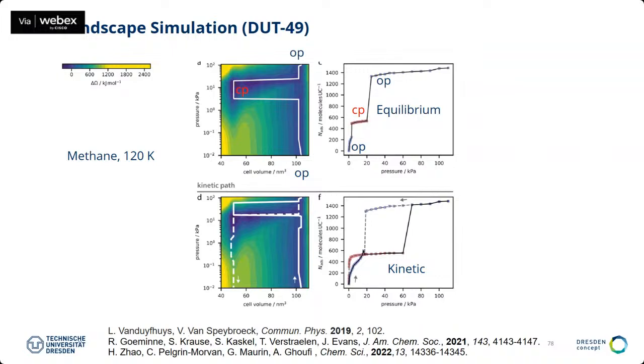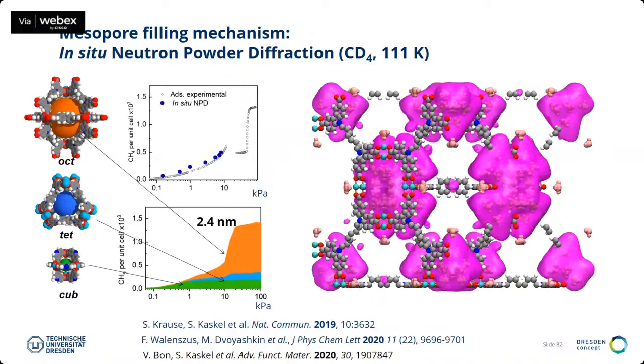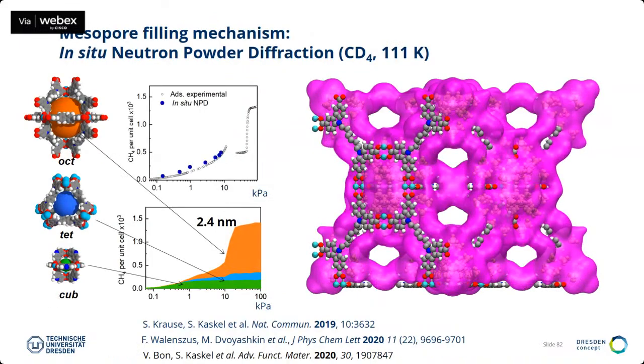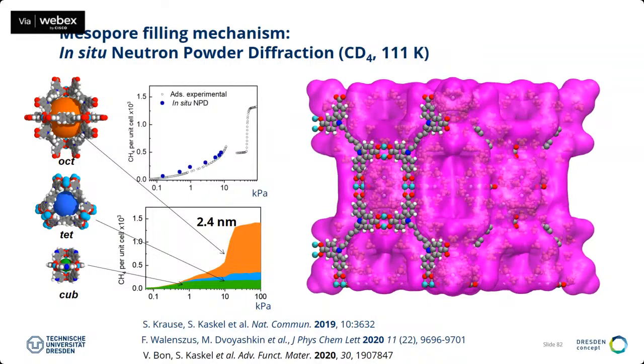These barriers are so high that you will not experience them in your lifetime. I mean, you always have to increase the activation barrier. You have to increase the energy to go over the activation barrier, similar as in catalysis, because these are exponential functions. So again, you can also use in situ neutron powder diffraction.